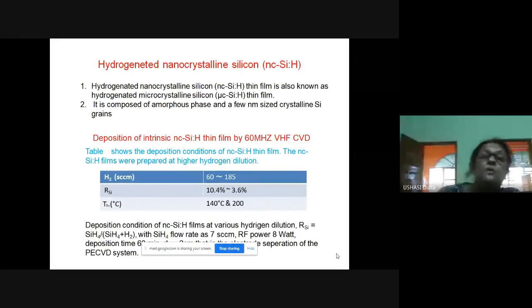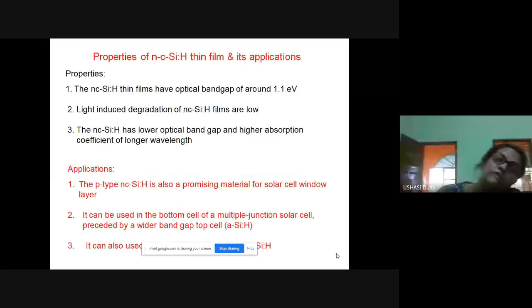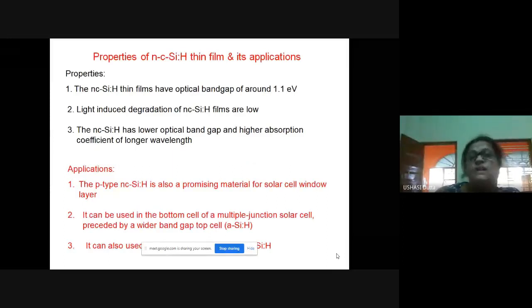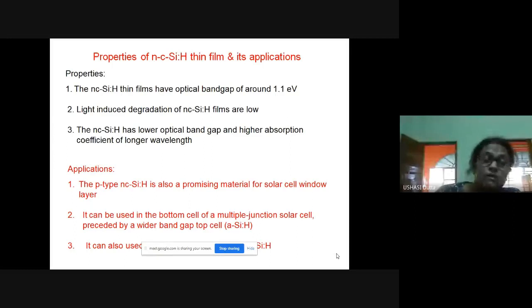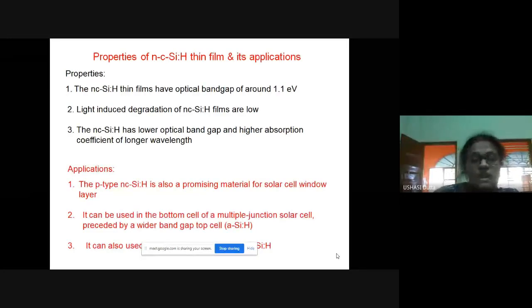And these are the properties of nanocrystalline silicon thin film. The thin film has a low optical band gap of around 1.1 electron volt, and its light-induced degradation is also low. Nanocrystalline silicon thin film has a lower optical band gap and higher absorption coefficient at longer wavelengths. So P-type nanocrystalline hydrogenated silicon is also a promising material for the solar cell window layer. It can also be used as the bottom cell of a multiple junction solar cell.